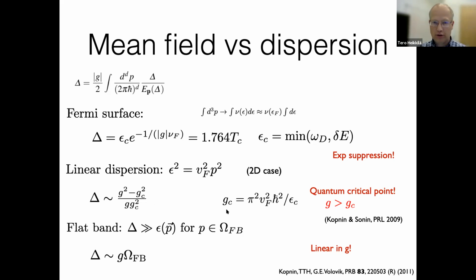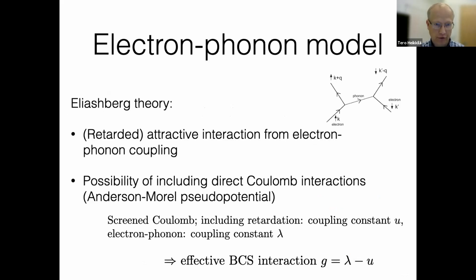On the other hand, if you consider this case of flat band, which is kind of the opposite of Dirac point, you get anomalous, very large delta, which is actually linearly proportional to this coupling constant times the area of the flat band. So it's linear in G, and presumably you should get much larger delta in this case. So these are kind of the extreme limits. In practice, of course, you need to take into account the details of the dispersion and study what happens. This is what we have done, but to give you some idea what different limits would correspond to.